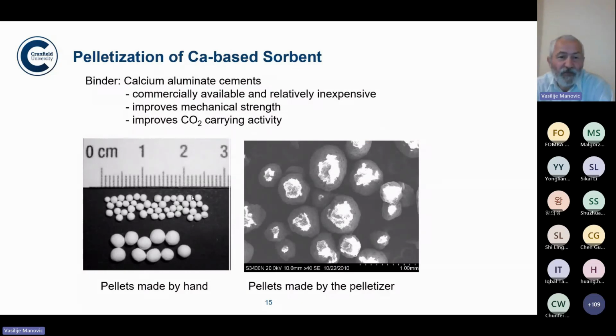One idea was using pellets, and that was one of the first tests, even when we just tried whether it would work at all, and we were doing that by fingers, so you see some pellet particles. But when we found that it worked, in that case we improved the mechanical strength of particles, we improved activity by hydration, and we had commercially available and inexpensive binders that we can also add to improve mechanical stability, such as calcium aluminate cements.